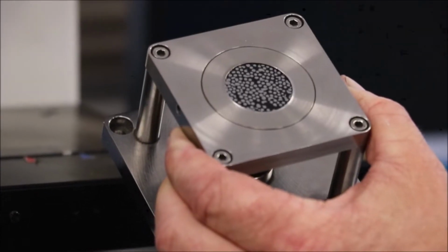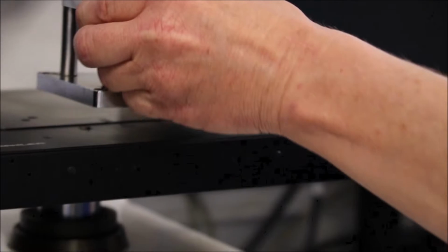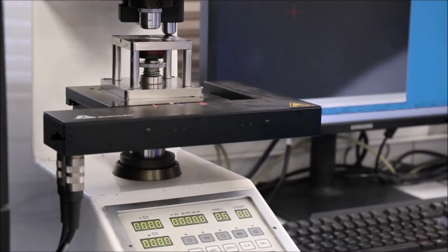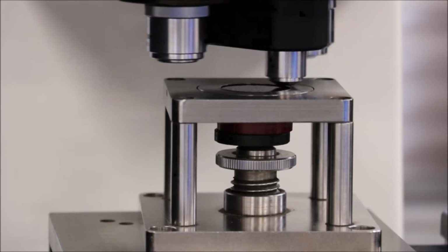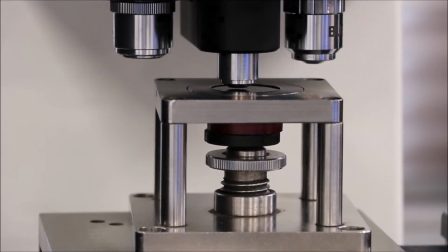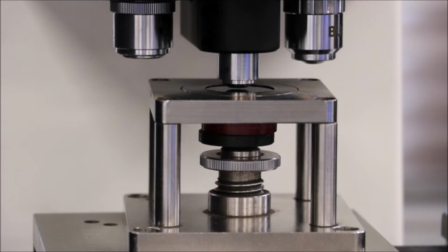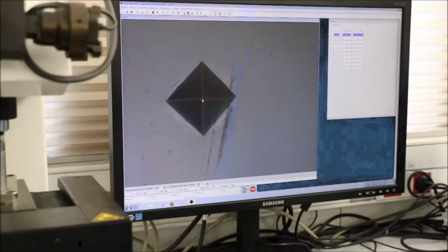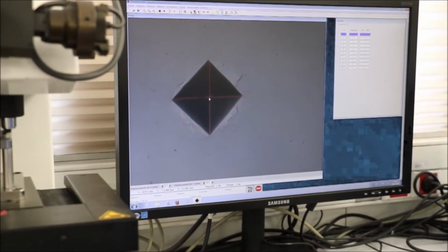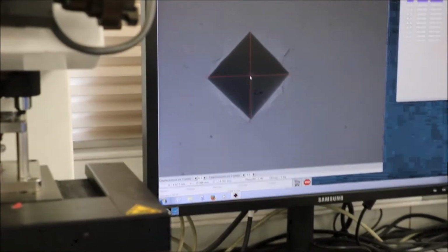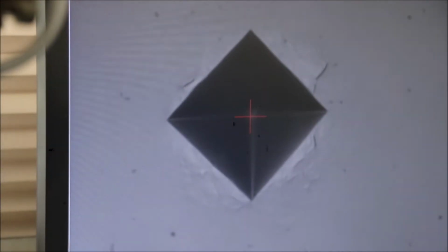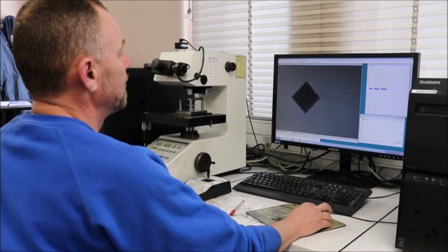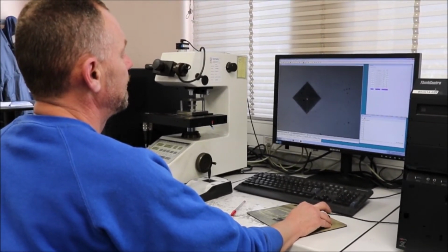Then, when the surface of the plug is perfectly polished, it's ready for the hardness measurement, which is based on the Vickers method, and you can find the principle on the WINOA app in one of the latest calculators. The area of the print is measured, I mean the trace of the probe inside the metal, and with a conversion table, the hardness is evaluated. We make the measurement in Vickers and the software automatically converts it to Rockwell C units.